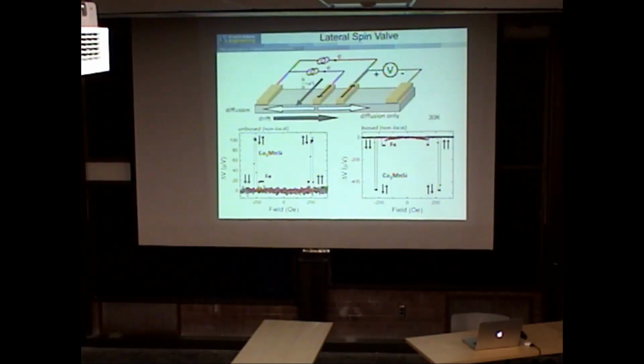Okay, now, what effect would all this have on if we made a spin valve? Okay, so let's do a comparison. So this is what we were doing in the past was iron. Here's a spin valve signal. Here is a cobalt-2 manganese silicon contact.